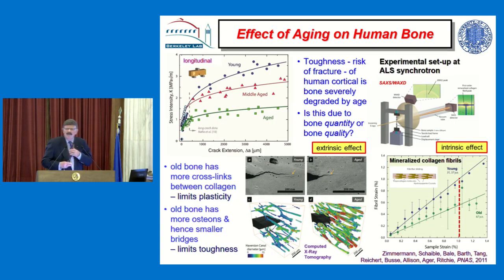One of the issues with bone is what happens when you get older. We know that bone's more likely to fracture when you get older. As I said, it's due somewhat to loss of bone mass, but it's also due to the resistance to fracture. This is the toughness of bone as a function of crack extension, and these are the resistance or R curves. This is the initiation toughness, this is the growth toughness. You can't see much on the initiation toughness, but this is young bone, 30-year-old bone. This is middle-aged bone, 50 to 60-year-old bone. And this is aged bone, which is maybe 80 to 90-year-old bone.